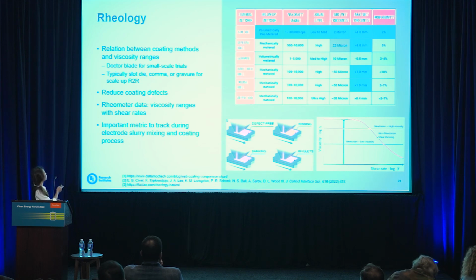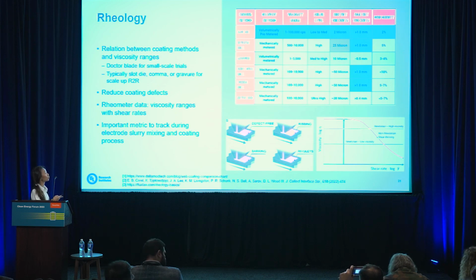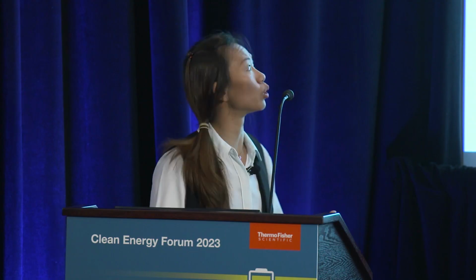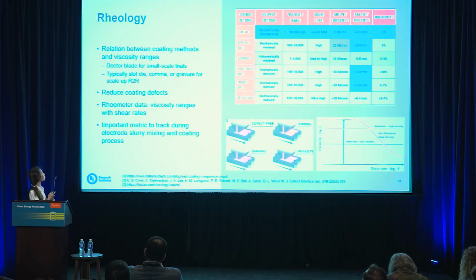There is a relation between coating methods and viscosity ranges, as shown on this table on the right. If your slurry is of a certain viscosity range, it means that you need a certain coating method to ensure a really good coating. Of course, Doctor blade is typically used for small scale trials, similar to a knife over roll. But as we scale out, we're looking at the slot die, comma or reverse comma, and gravure coating. If you're not well matched, you may have some coating defects, examples of which are shown here. I think ribbing is something that's very common, but there are other defects that can occur as well.